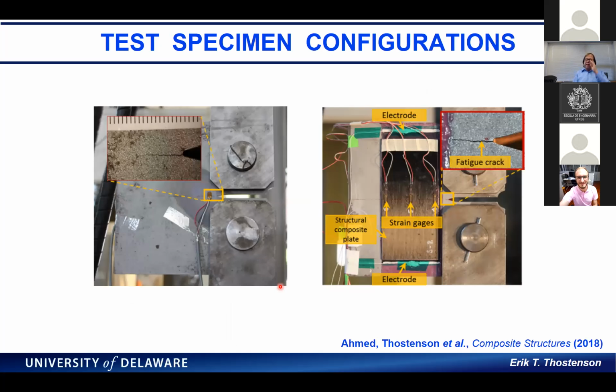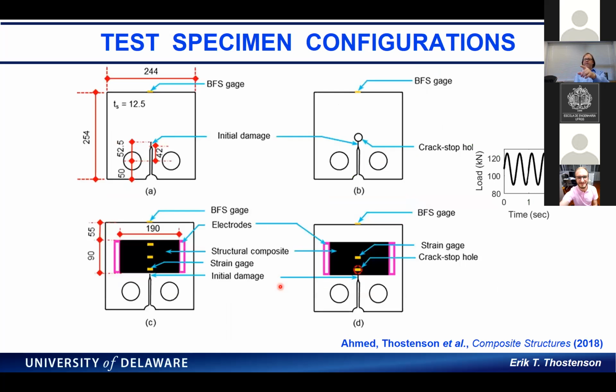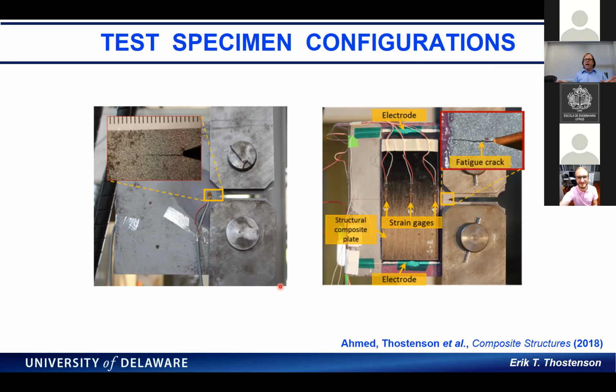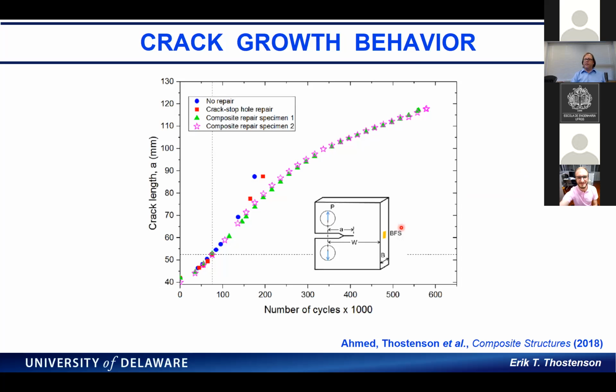Okay, so these are the specimen configurations. On the left-hand side, this is figure A, just our compact test specimen. You can see the fatigue crack right at the machined notch, and then we're just monitoring that until it fails. Here we've applied our composite repair and also integrated our sensor at the interface. So we monitor the crack growth behavior.